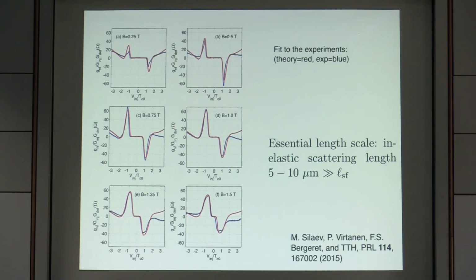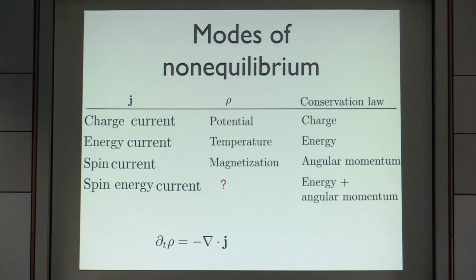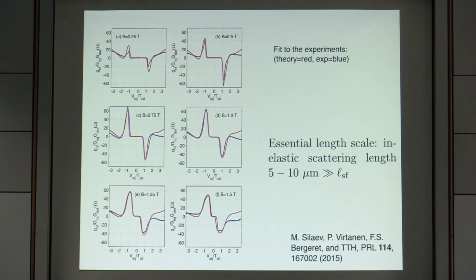Okay. For me, this is pretty convincing, but anyway. So the curves would have a different symmetry if it were spin flip? If they would be spin signals, yes. Yeah, they would be symmetric in that case. And actually, you can see that they have a small symmetric component also. The real issue is the shape of the curves, which is related with the inelastic scattering, and also the length scale of the inelastic scattering and how it scales with the magnetic field, which is still a little bit of a puzzle. But I think the origin of the signal is definitely this one, at least in the Karlsruhe experiments. Okay, maybe we see the opposite opinion after me.